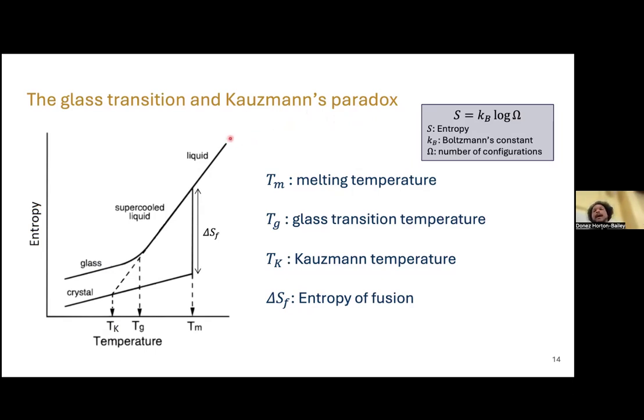Typically, you have 2 paths. If you start from a liquid, you cool it down. The typical path that we're used to is you get to some melting point or freezing point. At this point, all of the atoms arrange themselves into a crystal. During this time, the entropy is decreasing. There are fewer different ways that you can arrange your atoms into the crystal as you go down, and eventually you get fully crystallized. Every atom has found its correct position, and as you continue to cool, the entropy that is lost is due to vibrations and electronic effects. But this bottom line here is a fully formed crystal.